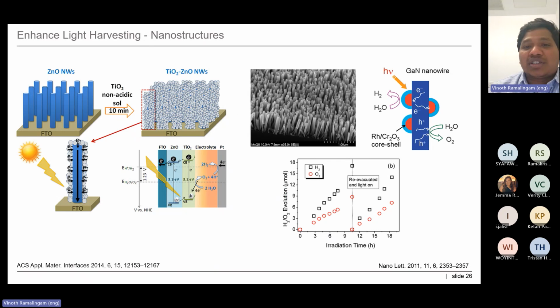Like microstructures, there are nanostructures. People have developed different nanostructured photoelectrodes that can again help to improve the light absorption ability of the photoelectrode, as well as show better charge carrier separation. As you can see, these are different nanostructures. They got TiO2 on ZnO nanowires, whereas here is a rhodium chromium catalyst on a gallium nitride nanowire device. So overall, what I'm trying to conclude here is that tuning the nanostructure and microstructure of photoelectrodes can help to improve the overall absorption of the photoelectrode, that can really help us to achieve better PEC performance.